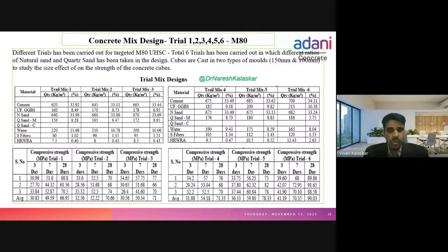In this, you can see we have done several trials. In trial mix 6, you can see this. We have added quartz sand, medium quartz sand, and natural sand. And if you see trial mix 6, we have added the same natural sand and quartz sand. So we got this M80 concrete, we got 90 MPa compressive strength. So this is the final mix design for compressive strength of M80.